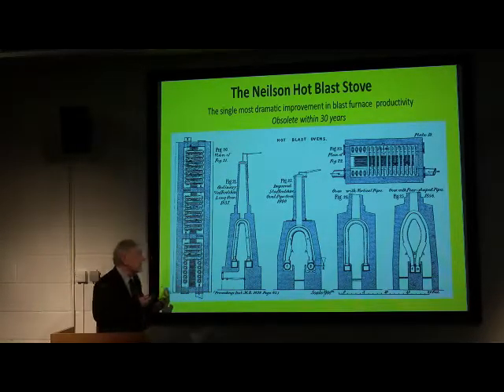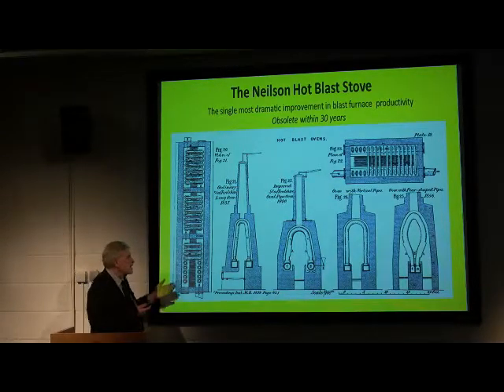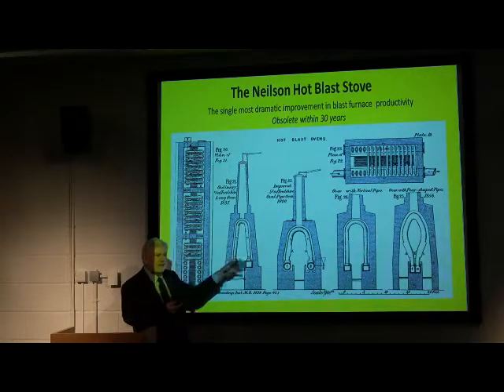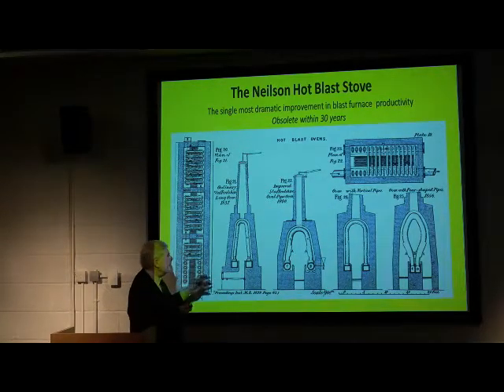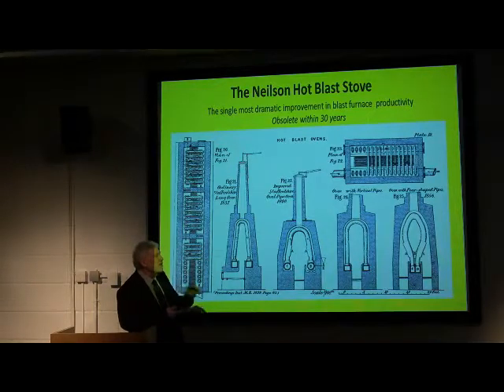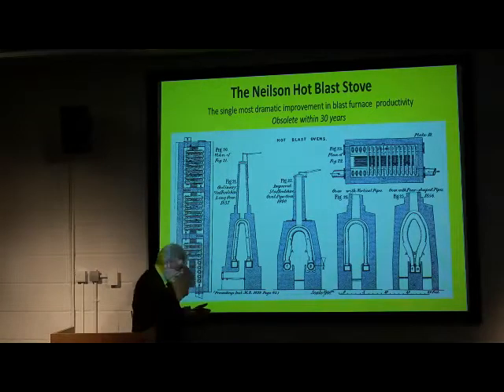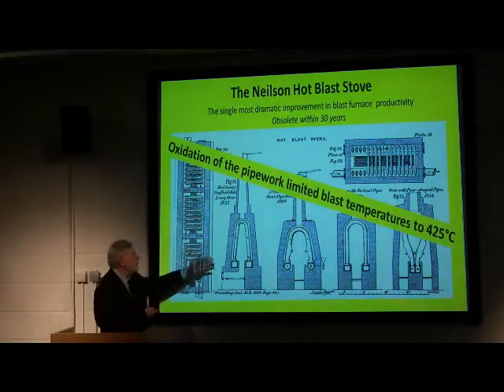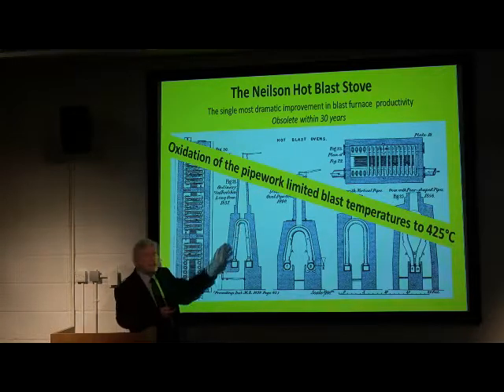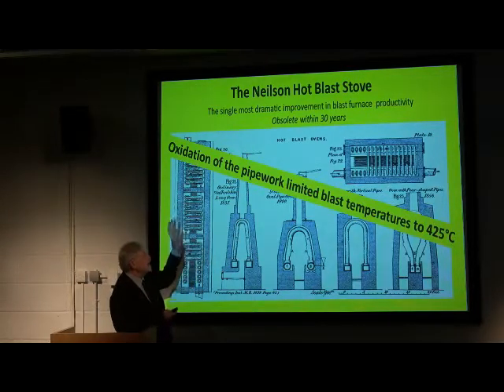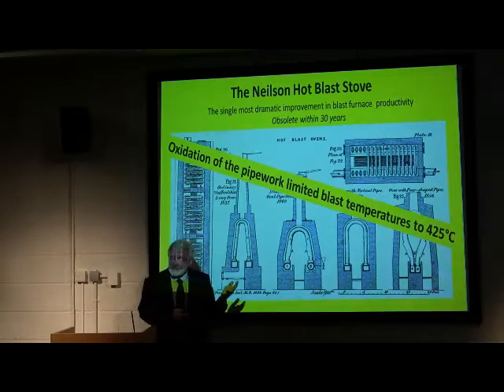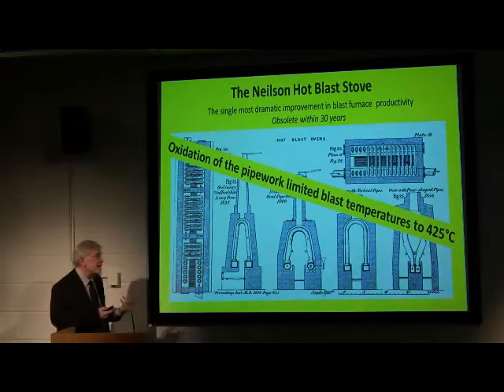And this technique of heating the air to the blast furnace increased productivity by about 50%. It was the biggest single development in blast furnace technology. And the Neilson stove was a great breakthrough. But the problem was that, once again, because you just had cast iron and wrought iron to play with, your blast temperatures were limited to just over 400 degrees.